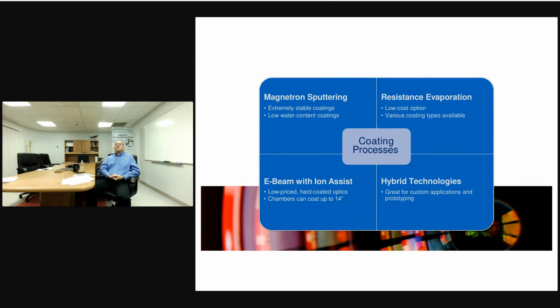So resistance evaporation is really the older technology. Here at Andover Corp, we've improved on the older technology. These are coatings that usually are assembled and laminated in. The indexes are further apart, so you can actually put less layers down, create low-cost options. You can make ultra narrow bands at probably a tenth of the cost of hard coating. And there's some really good price points. We always try to introduce the resistance evaporation into the formula, depending on some of the things that we talked about, your environment. If you're in a lab environment and not hostile conditions, resistance coatings are very, very good and a very smart choice for affordability.